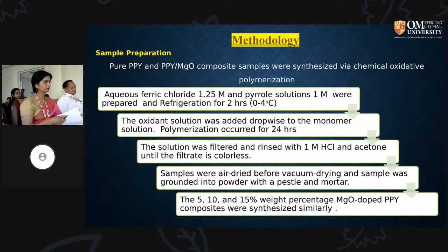Polypyrrole and polypyrrole with magnesium oxide composite samples were synthesized via chemical oxidative polymerization. Aqueous ferric chloride and pyrrole solutions at 1.25 molar and 1 molar concentration were prepared. After that, the solutions were refrigerated for 2 hours. After that, an ice bath was kept with the monomer solution between 1 to 4 degrees Celsius. After dropwise adding the oxidant solution to the monomer solution, the polymerization reaction commences quickly and lasts 24 hours.